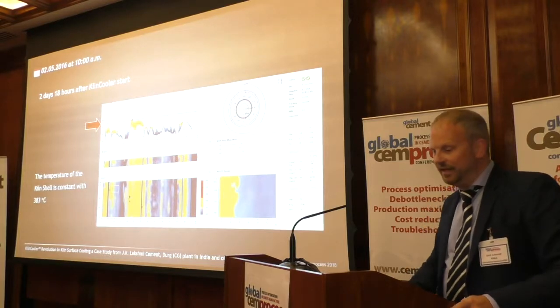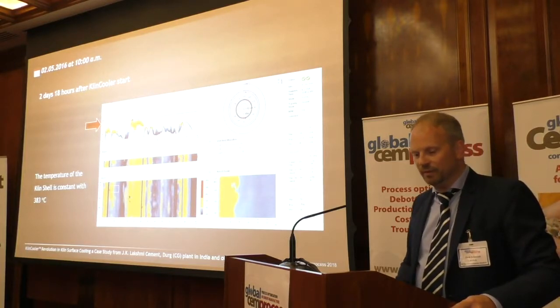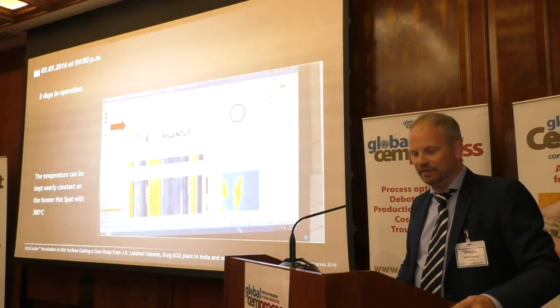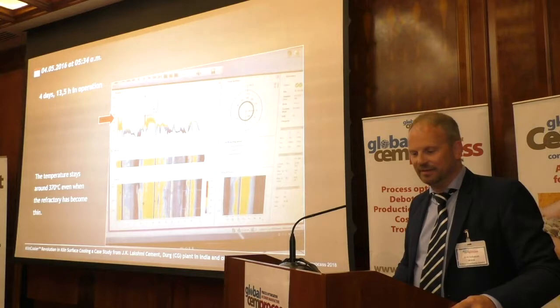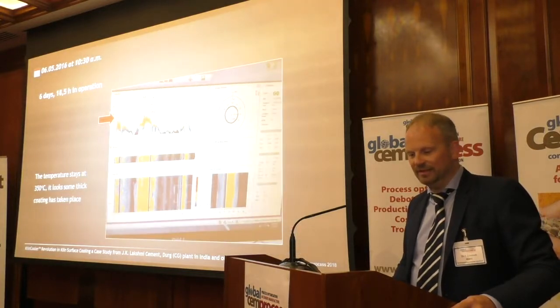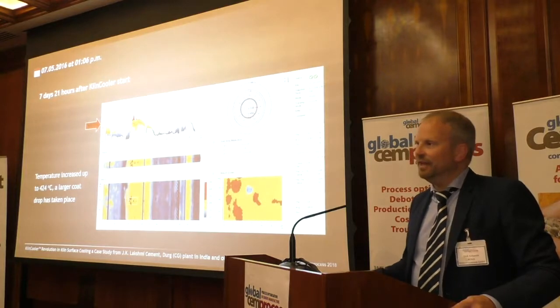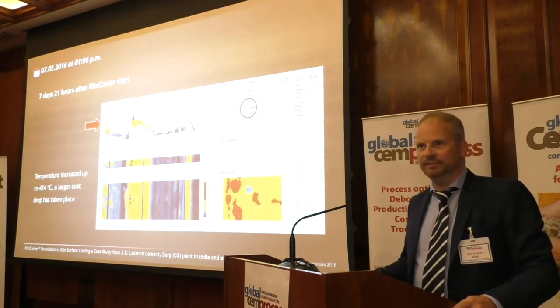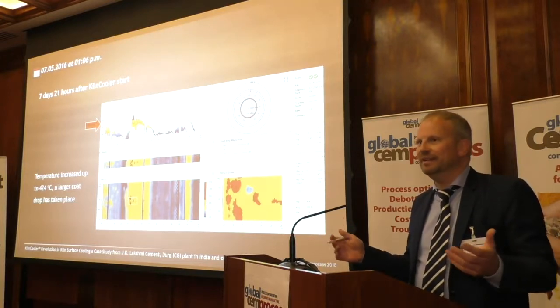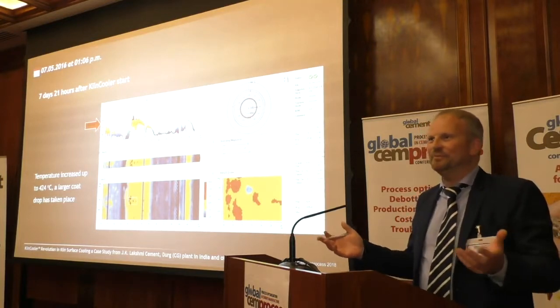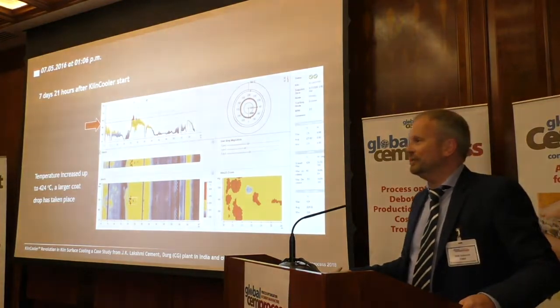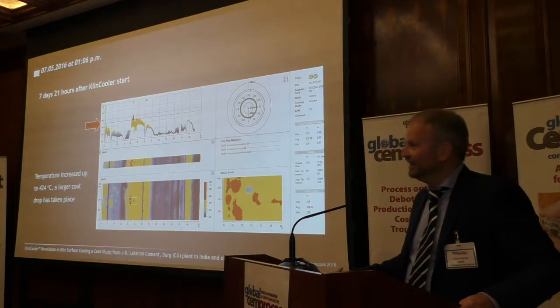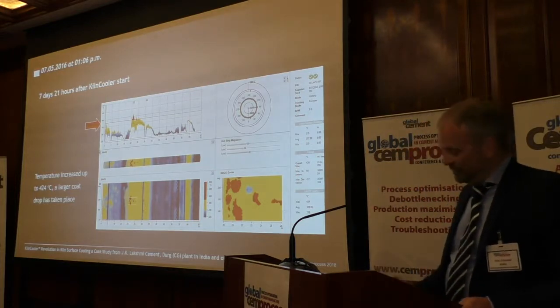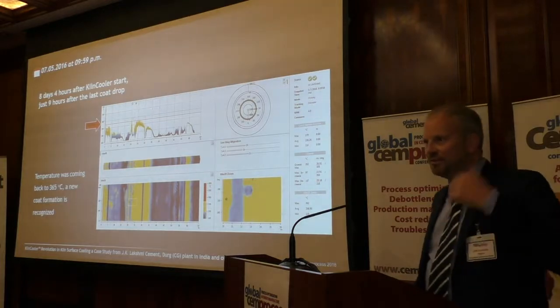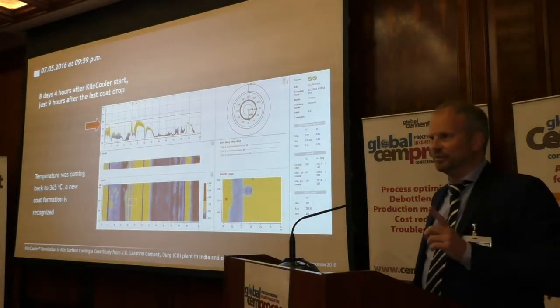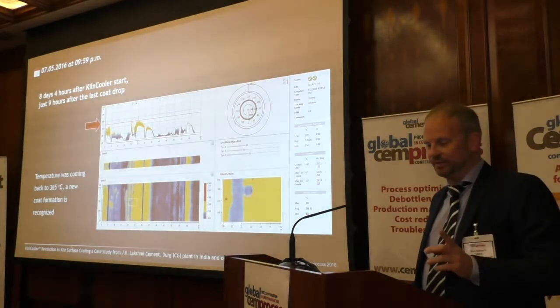So, after 2 days and 18 hours, we still have these small peaks with 380 degrees maximum after 3 days, 4 days, 5 days, 6 days. At the 7th day we have massive coating drops, and that's normal. At a specific time the refractory is gone, and then you can't prevent anything anymore, otherwise all the refractory material manufacturers would be very poor people. In this moment, of course, the system was again able to keep the kiln in operation under full production load. I must say that, always under full production load.